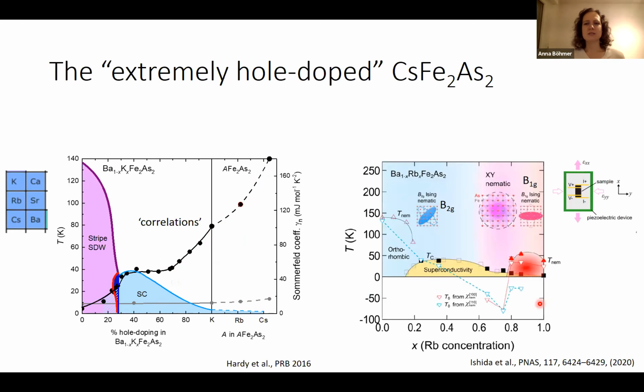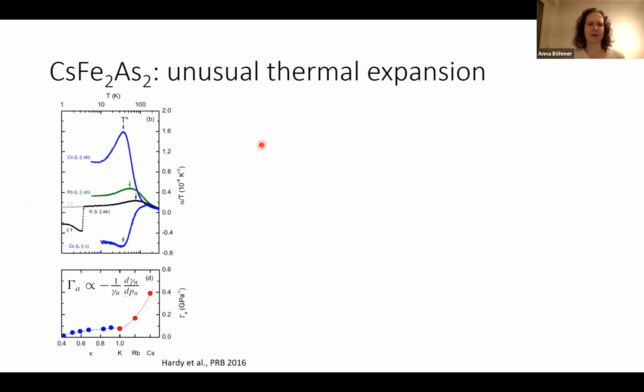There has been a recent report about nematicity in these compounds, going from the barium directly to the rubidium one. And what was reported is a flip, a change from a B2g type nematic behavior to a B1g type nematic behavior. So a flip of the nematic directions, deduced from elastoresistance measurements. We wanted to start with the most extreme compound, the cesium 1-2-2 here.